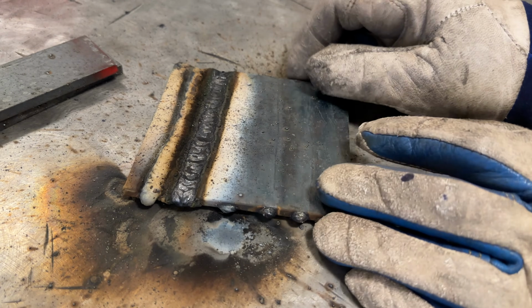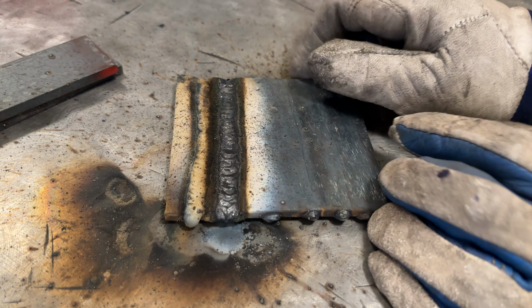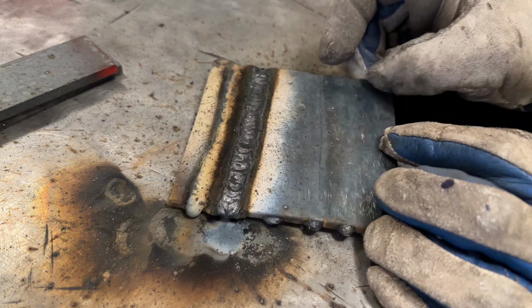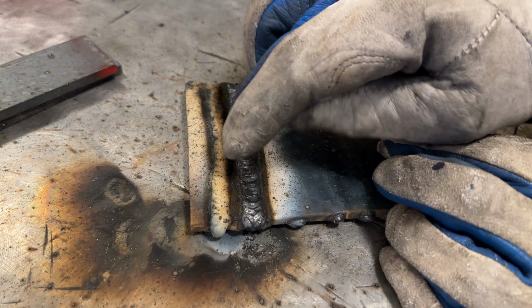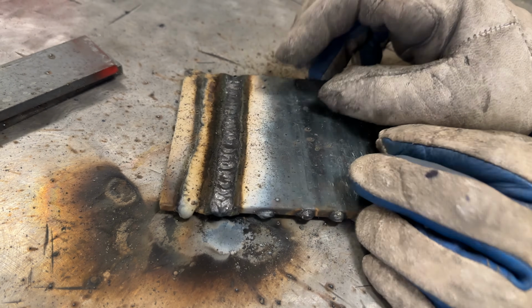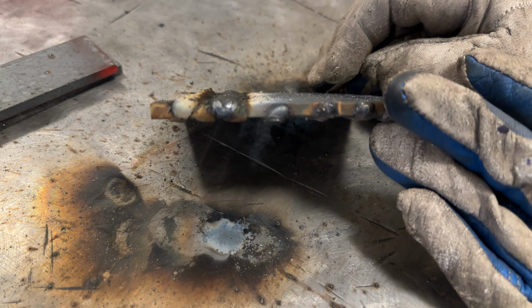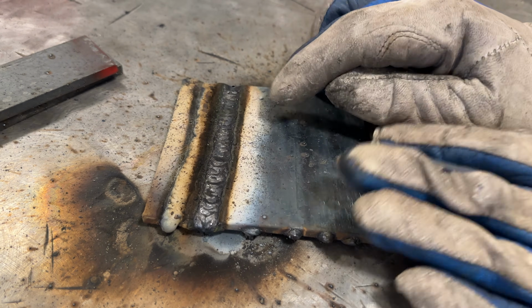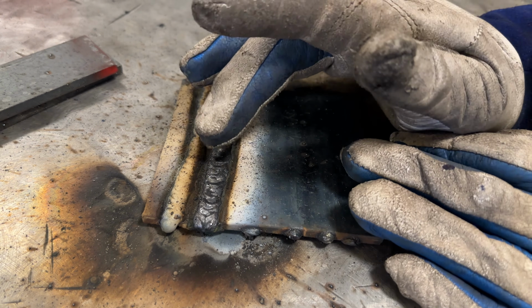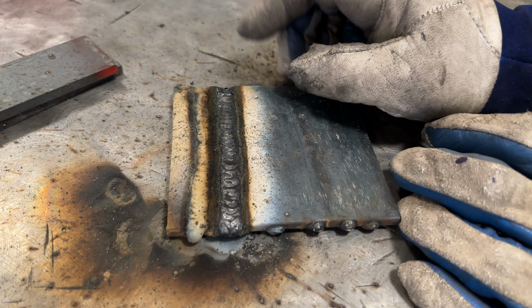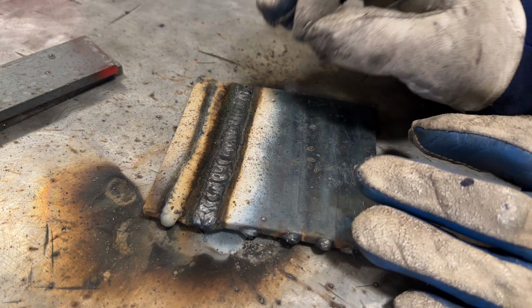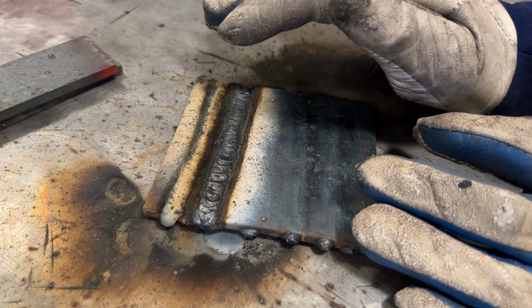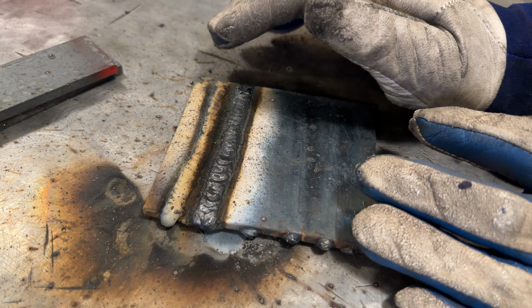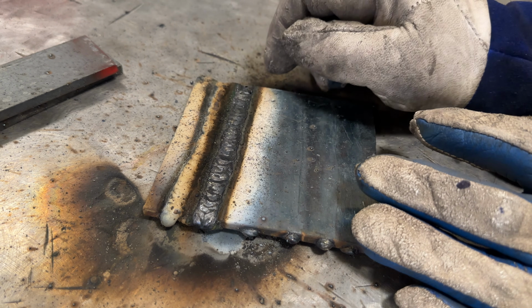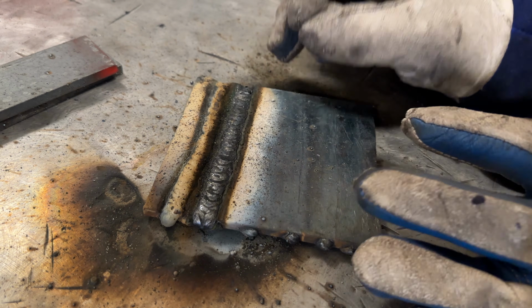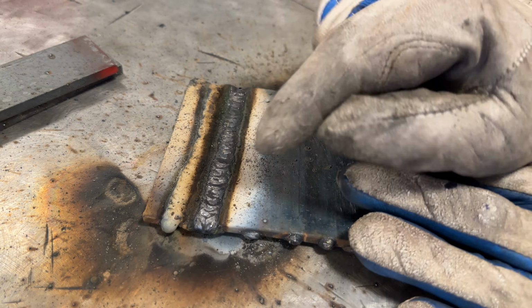So a couple things to note before I go clean this off and cool it. If you look at the first bead, and again, this has flux on it, I didn't clean it. It's far more humped up than the second bead, which laid flatter. And the reason is that I find 6011 needs slightly more amperage than 6010 to lay flat, or if the plate's heated, it tends to lay flat, because I used new rods for both of these.